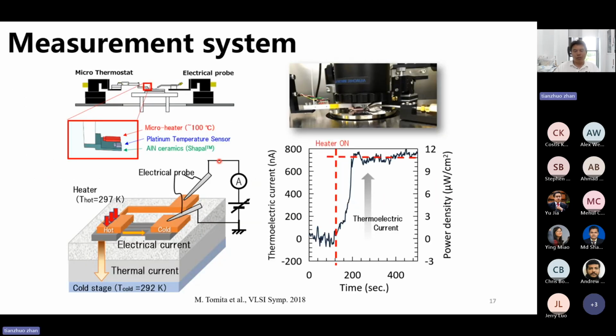And so we also measure the thermoelectric properties using a lab-built measurement system. We use a micro heater to heat the hot side junction, and also we use a chiller to cool down the cold stage, and this acts as a cold side junction, and then we can form a temperature difference across the silicon nanowire.